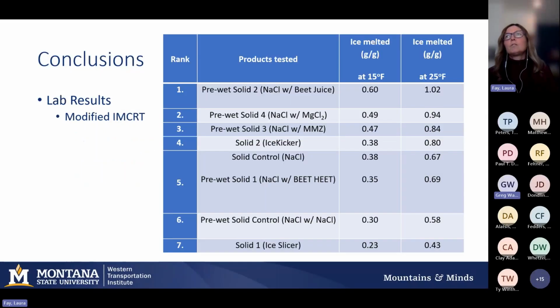So getting into the modified ice melting rocker test, these are the results from top performer number 1 down to, I guess, the least ice melted. And for both tests, at both 15 and 25 degrees, sodium chloride pre-wet with beet juice had the highest ice melting capacity. But again, most of the pre-wet rock salts with the additives that were identified had the higher ice melting capacity rates, followed by ice kicker, and then the control products, beet heat, the pre-wet control, and then ice slicer.